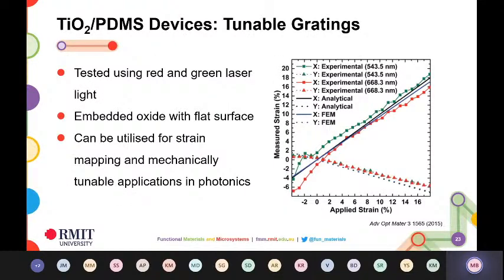Just some graph which shows you the measured strain and the applied strain. So you can kind of see how the experimental results using red light and green light match up with the analytical and the finite element modeling results. This was some of our early demonstrations. So our imagination then was this could be used potentially for strain mapping. And it's also a nice demonstration of a mechanically tunable application in photonics.